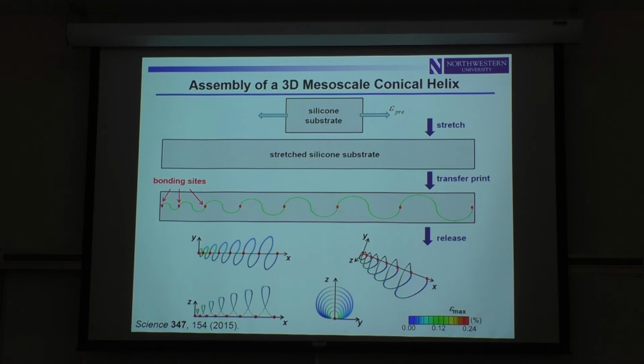So now, if it's OH functional groups on the silicone substrate and on selected regions of this released filament, such that when we bring those two things together, those exposed OH groups react with one another, give off a water molecule, and lead to covalent bonding at that interface, a strong adhesive bond.